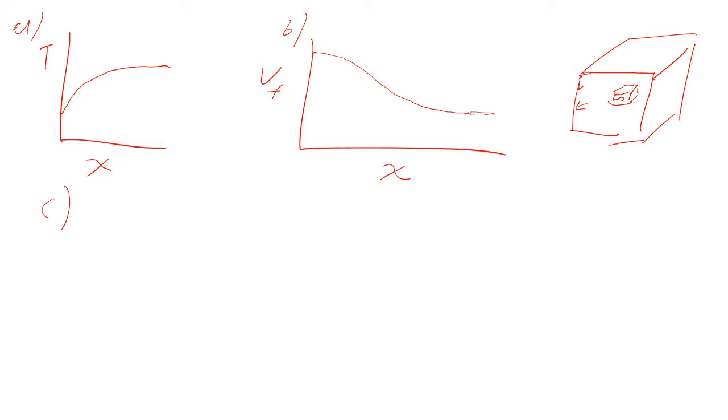Okay, so think about it from just a thermal expansion point of view. You've got a uniform ball at high temperature. The surface cools more rapidly than the inside. Eventually the surface reaches a point where it doesn't flow anymore, but it has been shrinking relative to the inside.